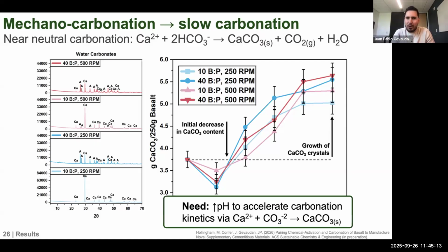But of course, you're probably wondering, well, that is very, very slow, right? We don't have 8 weeks to carbonate and mineralize CO2. We need to accelerate this carbonation. So what we need is a higher pH, because we know that at higher pHs, the deprotonation of that carbonic acid happens much faster, and we can form calcium carbonate and magnesium carbonate much more rapidly.